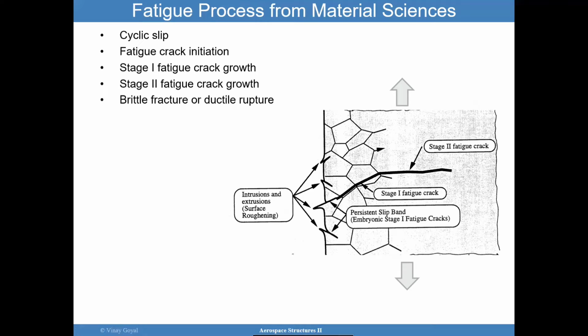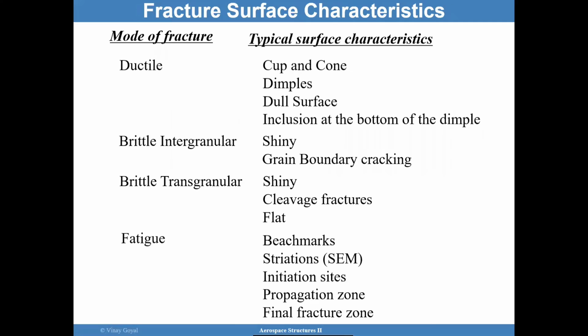So the fatigue process from the material science perspective is cyclic slip, fatigue crack initiation, stage 1 fatigue crack growth, stage 2 fatigue crack growth, brittle fracture, or ductile rupture, okay? So it's really important to understand that there are these processes that occur microscopically and then turn into macroscopic crack growth, and all of that has to do with the persistent slip bands that we talked about. And you're going to have some surface roughening because of that. Sometimes you get some sort of peeling indication of the surface. So the fracture surface characteristics are important to understand, especially in failure investigation.